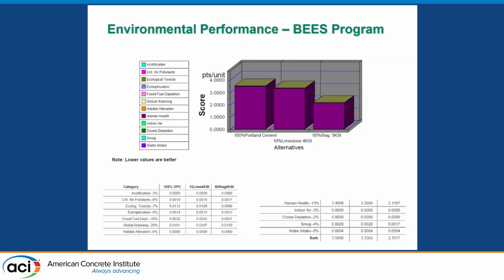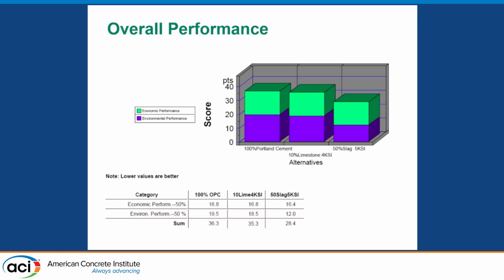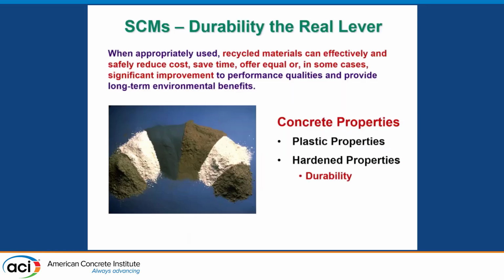This is the BEES program, which isn't used much anymore. However, to do a proper EPD, we still don't have an EPD yet for silica fume, and fly ash doesn't have an EPD either, so we don't have those figures yet for the reduction in CO2, but they're forthcoming shortly. And so we can see the overall performance, that if we talk about the economic performance and the environmental performance, using blended cements is actually much better than using a straight Portland cement. And so certainly I won't linger on this. We know that you can change the plastic and the hardening properties. This is an old slide, an oldie but a goodie, so we're all laughing at it.